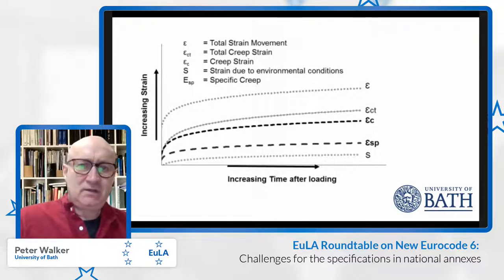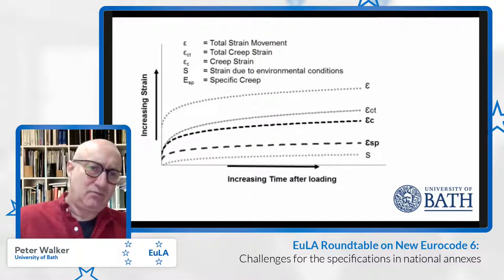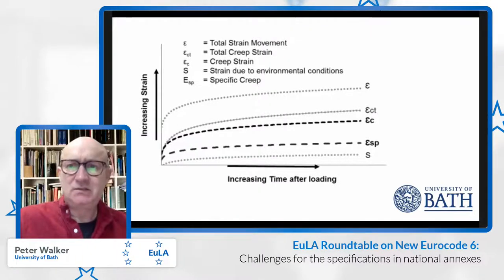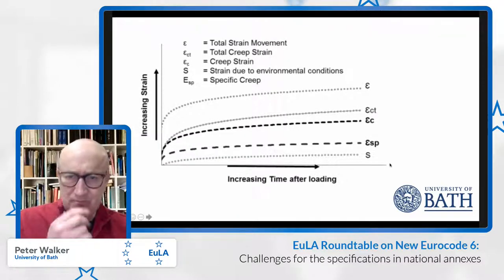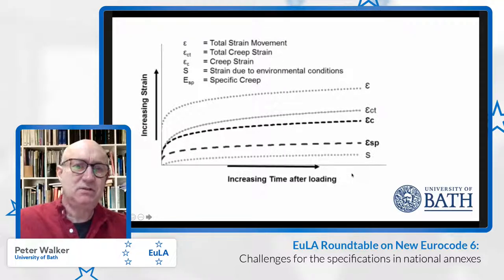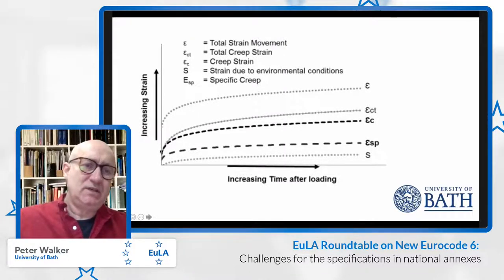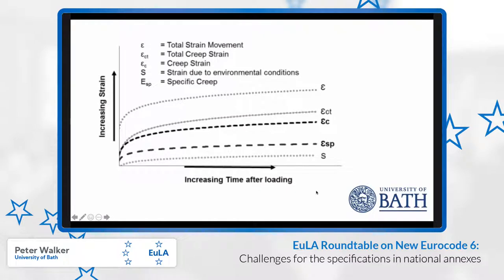Moving on to looking at the creep testing, before presenting the results, this graph here, just to explain how we presented the results, shows the increasing strain with time. Creep is a time dependent movement of the material in response to a constant applied stress. What we have measured in each of the specimens is the total strain movement, epsilon here, as represented by this top curve here.